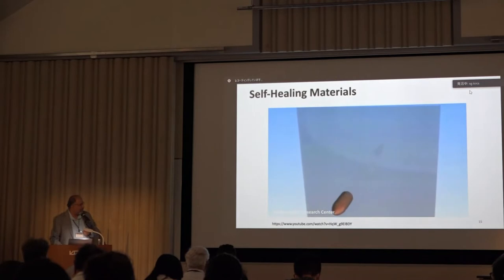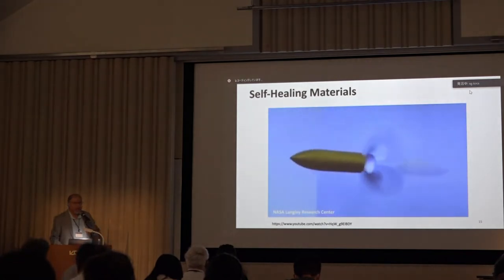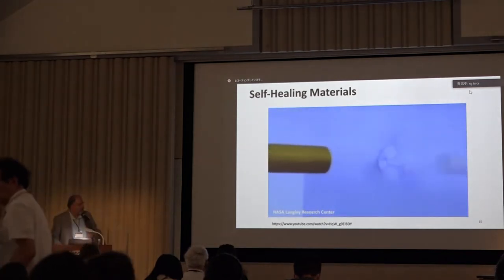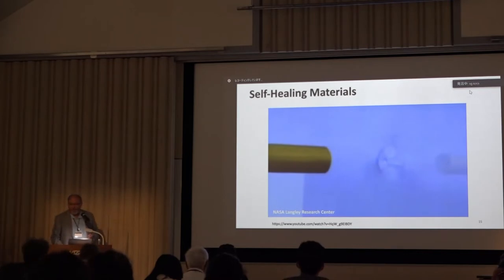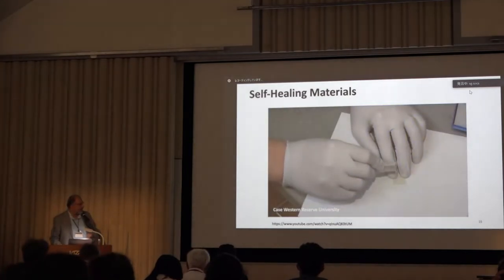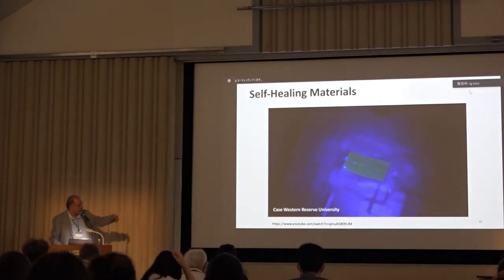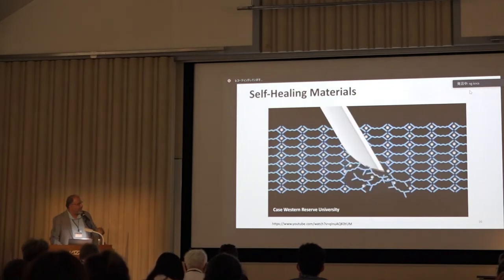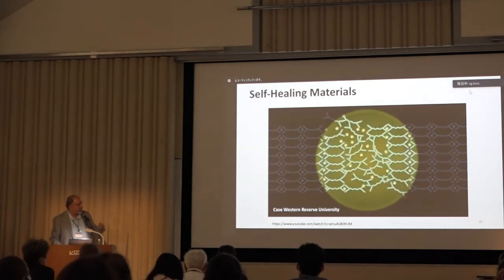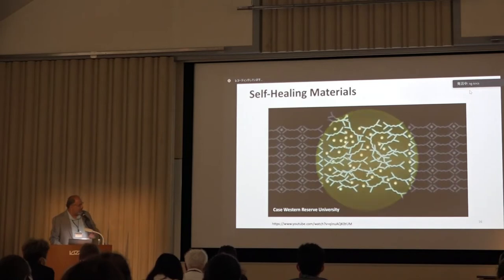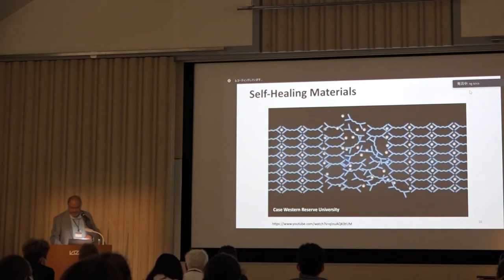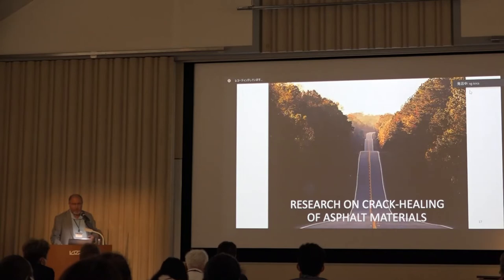This is another example from NASA. It's a very ambitious program to create self-healing materials for spaceships. Spaceships are much more expensive than asphalt, so they can afford more expensive solutions like specific monomers that we actually tried in the asphalt a little bit. And this is another case from Case Western Reserve University of a coating material that, when cut, redistributes and rearranges itself and creates self-healing.